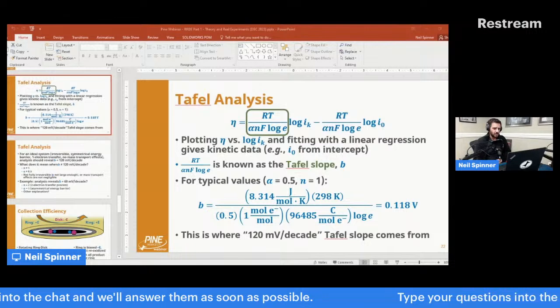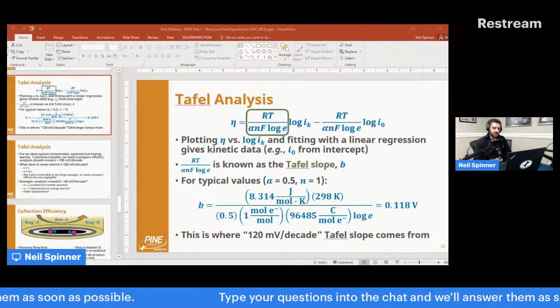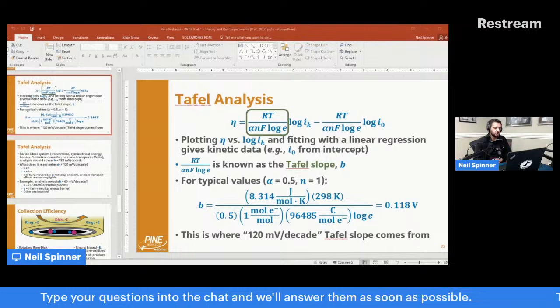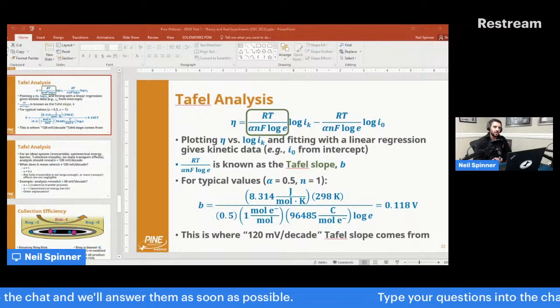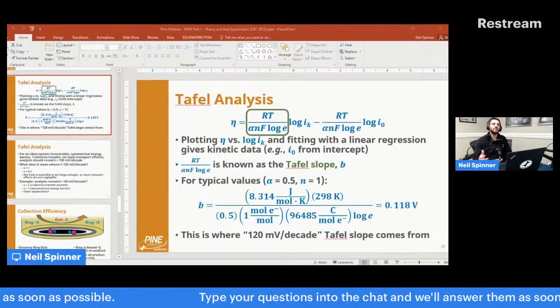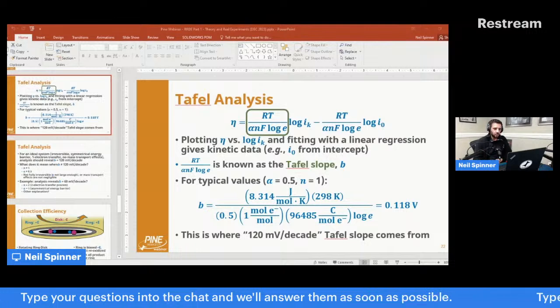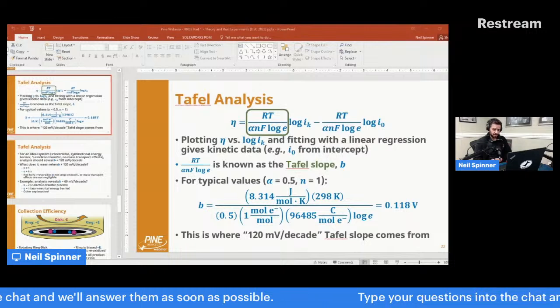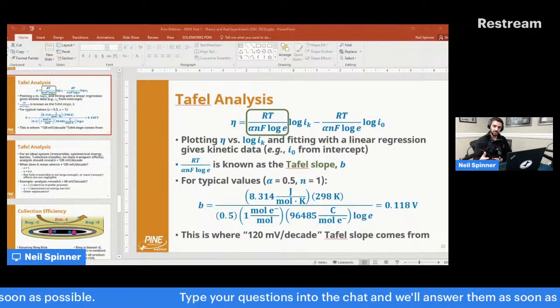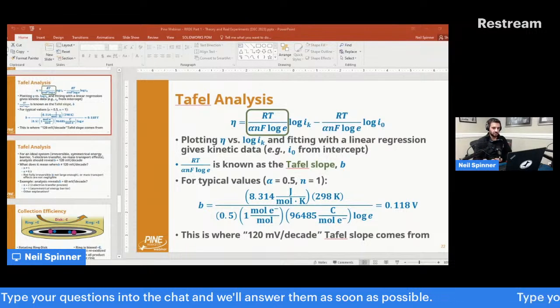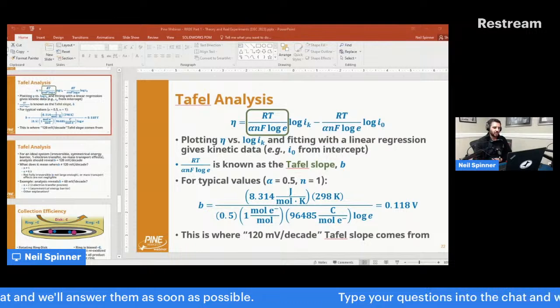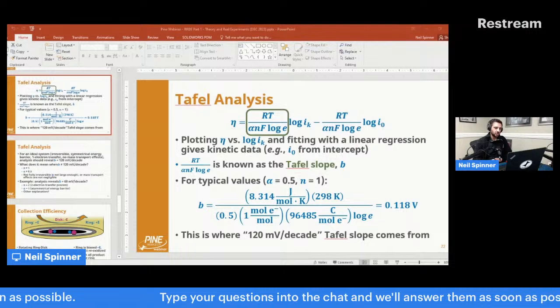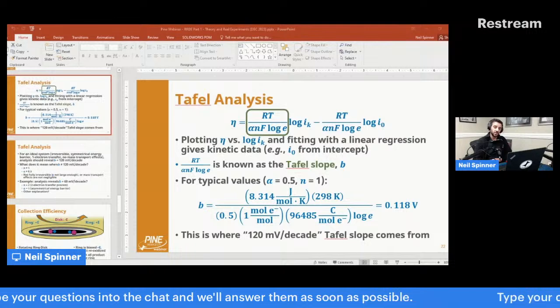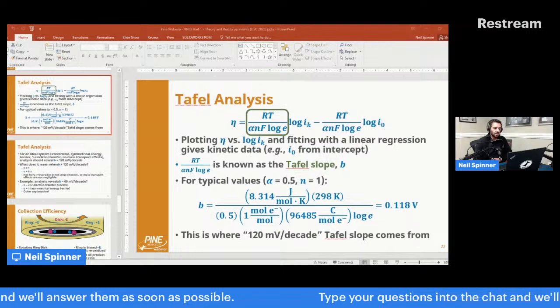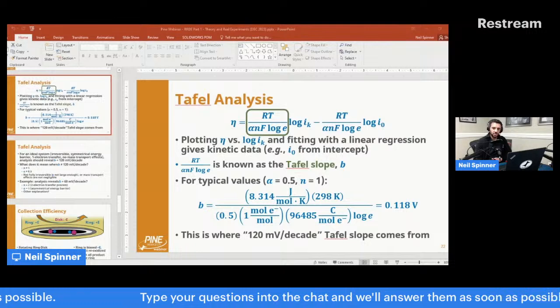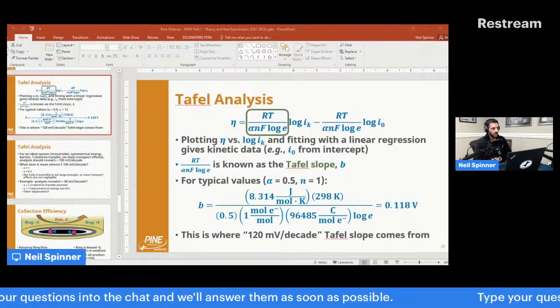And so the importance of the Tafel equation, or the Tafel slope, I should say, is that it gives you direct insight into the kinetics of whatever you're studying. Now, again, as I mentioned before, built into that is the assumption that you must be looking at kinetic information, which is to say kinetic current, and not just any current collected on your electrocatalyst. But if you're able to do that, you can get things like the Tafel slope, which changes depending on the alpha, the symmetry factor, which is often just 0.5, and changes based on the temperature. You can see how the temperature changes the kinetics by looking at how the Tafel slope changes. And then n, the number of electrons.